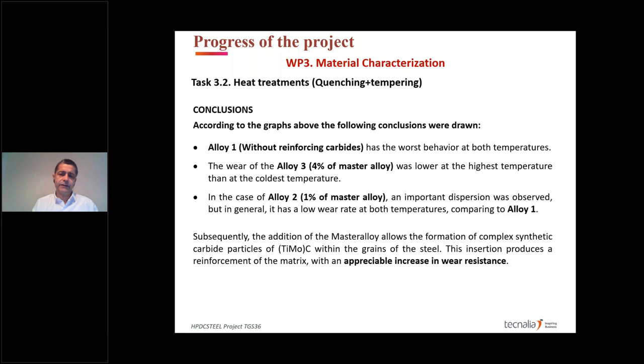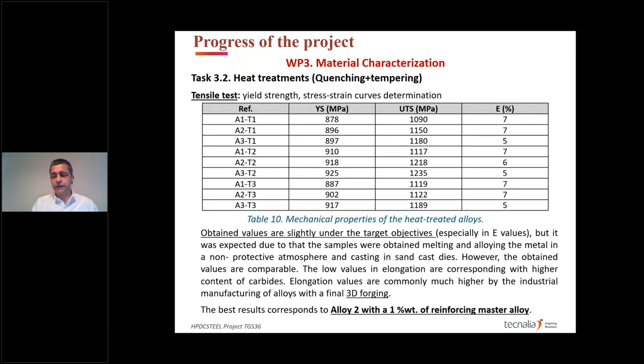the better properties, but not always. There was no clear difference between the alloy with 1% of master alloy and 4% of master alloy. So we see that there was an improvement in wear, but the percentage of master alloy was not so determining after 1%. Having 4% was not so determining.